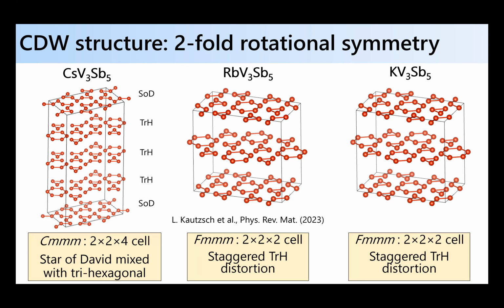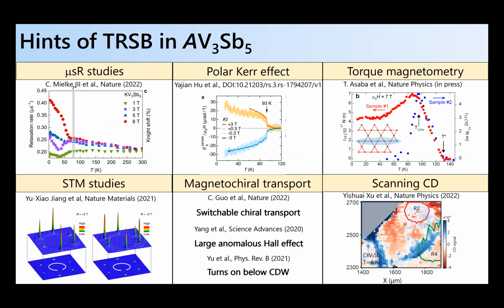In the cesium system, the charge density wave state seems to be much more complicated. Now, this is what the average structure is. There's this local structure in there that I'm happy to discuss if anyone's interested in details, but it has a larger supercell in the average sense. And it seems to be comprised of a mixture of both Star of David and trihexagonal distortion types. All of them are centrosymmetric? Centrosymmetric. Yes. Okay, so that's sort of the standard real part of the charge density wave order.